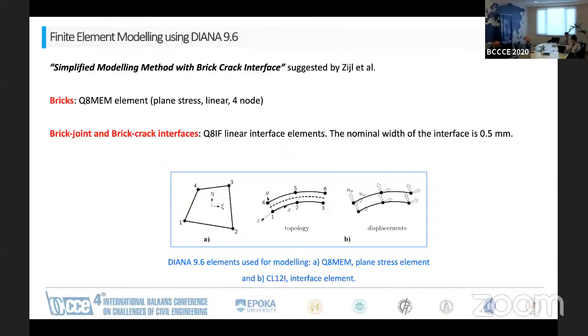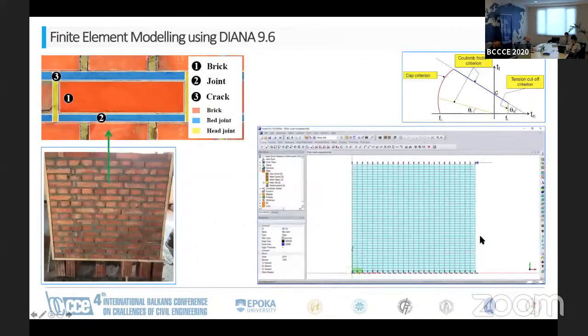We also did a finite element modeling using Diana software, using a simplified modeling method with brick crack interface, where we had to model bricks and brick joints and brick crack interfaces using some elements that the program already possesses. So we had these elements, Q8MEM and CL12I interface element. This is how we modeled the panel. So we had to consider the brick, the joint, and the cracked interface, as well as we ran the analysis.